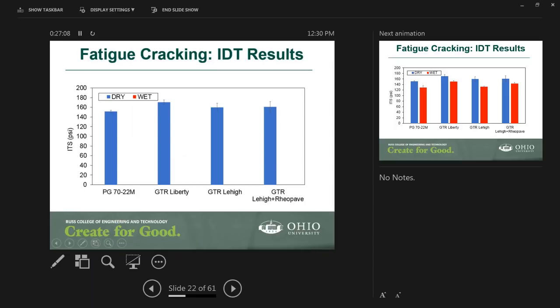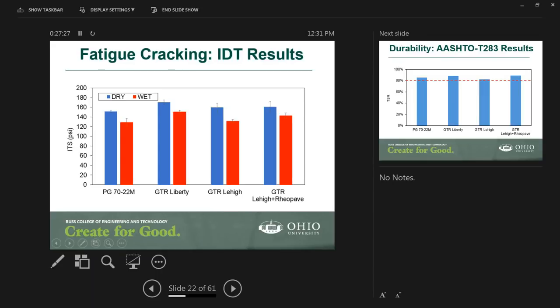Here I'm showing the indirect tensile strength, and again we have seen an increase in the indirect tensile strength of the dry sample for the GTR. Once we used a GTR modified binder, the highest was with the Liberty, but again it was not much different. Upon conditioning, mainly the wet conditioning, again the indirect tensile strength dropped. And the wet condition samples had the same trend in all cases, for the polymer modified as well as for the GTR modified. We had a very similar trend.